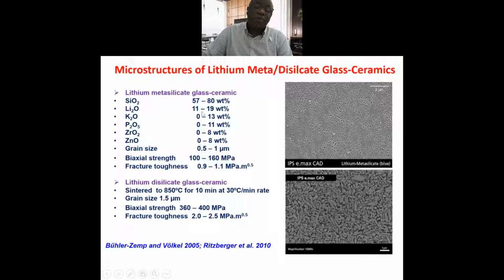They use the process of glass when they heat in a glass batch. Then from there, the ceramic material will also initiate. That is the lithium metasilicate. However, the grain size of the crystals, like lithium metasilicate crystals, is very small, and so are the biaxial strength and fracture toughness.